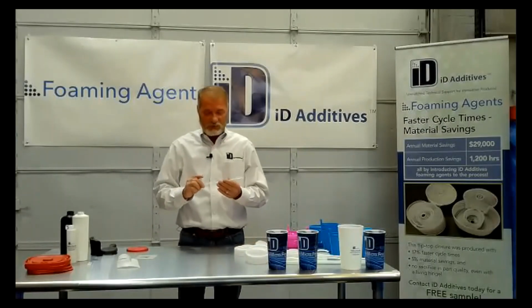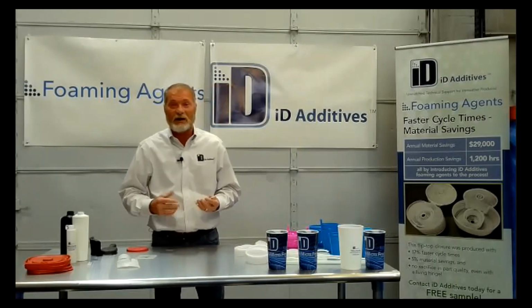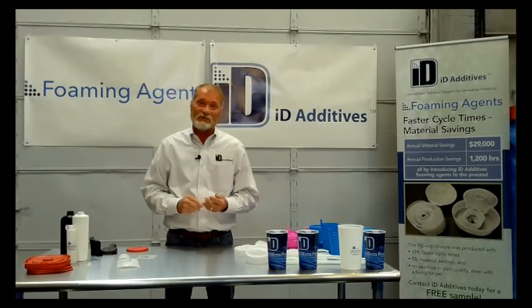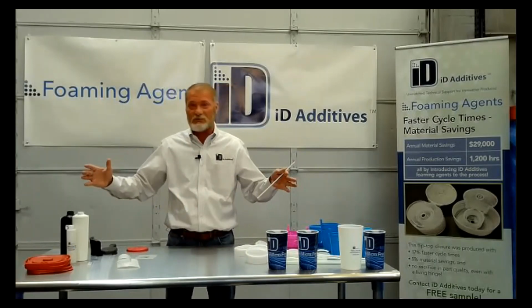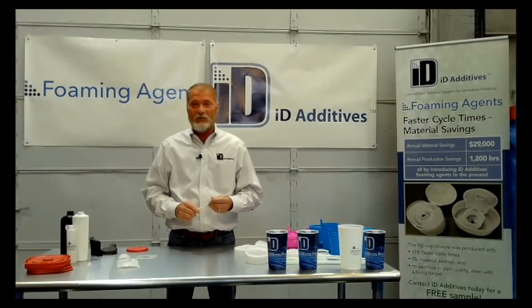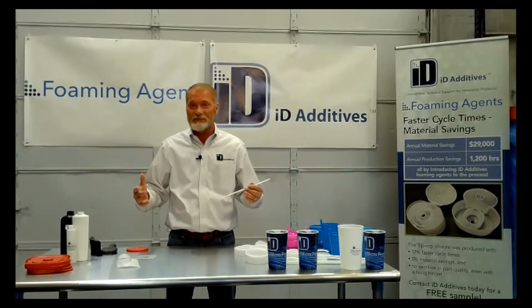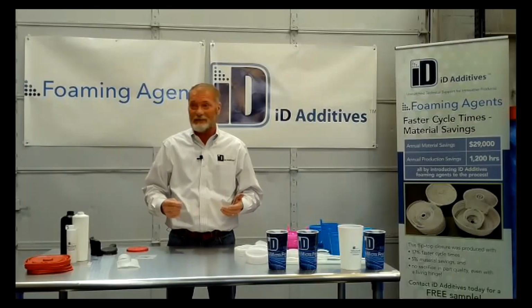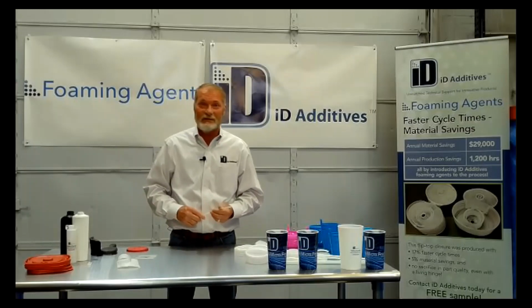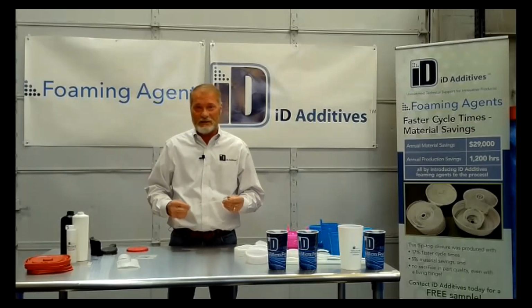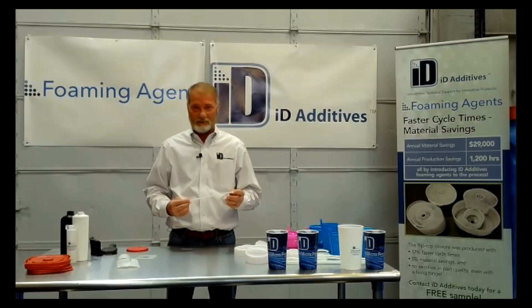This thing was going so fast, I had to bring the temperatures up because it was going so fast in a small extruder that the foam just didn't have time to go off. It was crazy. So I went up like 25 degrees, but it didn't affect the temperature of the part.